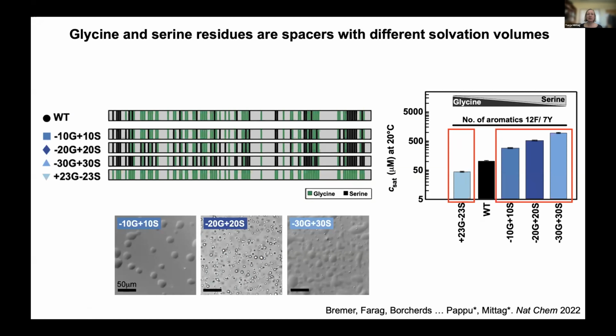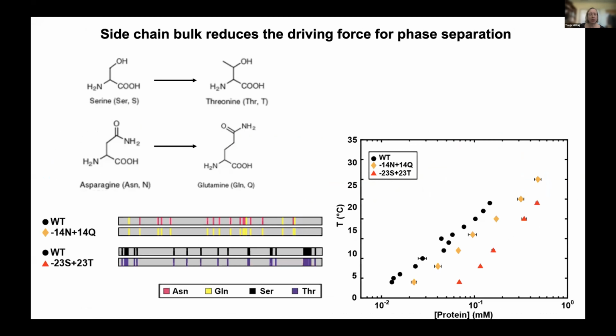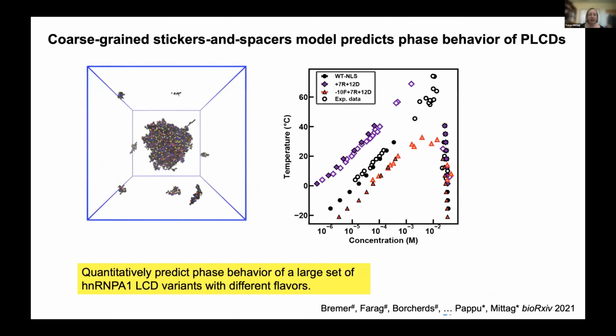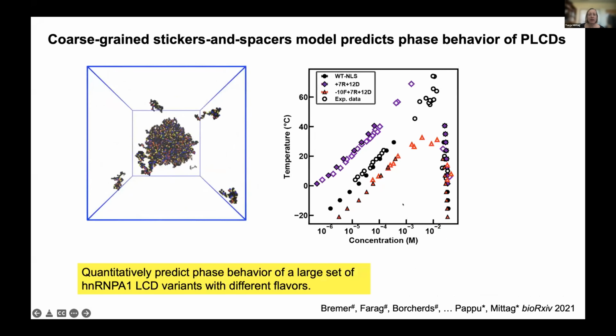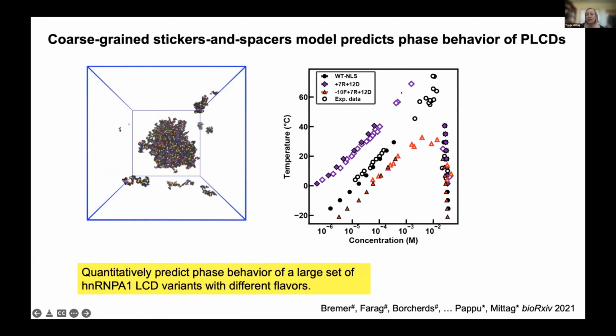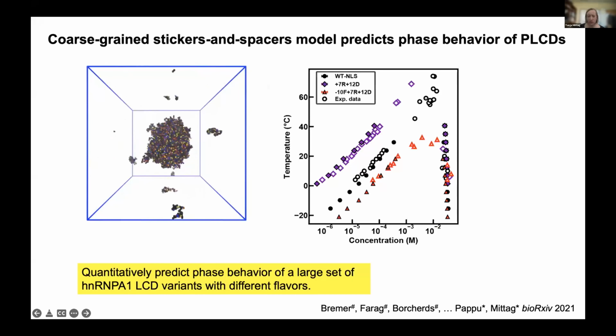We can play these same kinds of games also with other polar residues like asparagine to glutamine or serine to threonine, and we always see that the larger spacer will interfere with phase separation more. Oh, and there is actually the data. When we're going from serine to threonine or from asparagine to glutamine, we're weakening phase separation. Rohit also showed you that they can extract all of the interaction parameters from our single chain dimensions and can really simulate the phase behavior of our variants very well, even of variants that we haven't used in the parameterization.